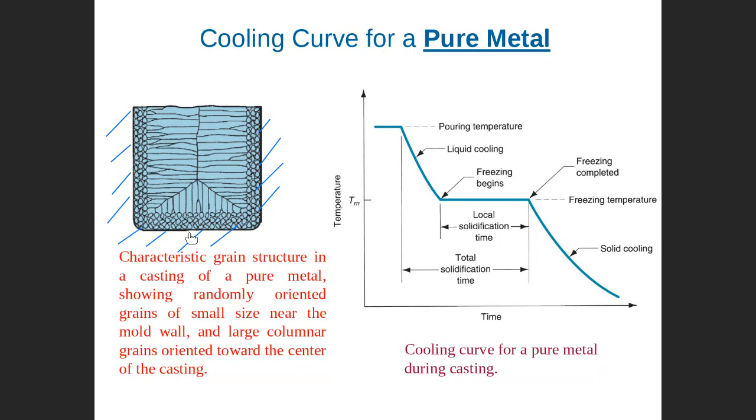So solidification starts at the beginning on this layer, which is very close to or in contact with the mold, because the higher heat transfer rate is here. Later, the material in the core will solidify. The grain here on the outer fiber is a nice, fine grain, but later the grain inside is stretched because this material didn't solidify yet.